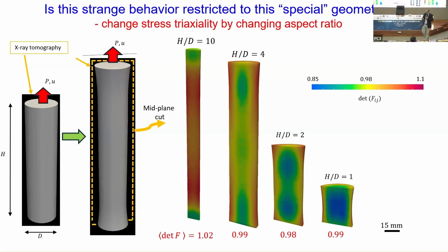And now what you can see is that this very long specimen was nearly incompressible in the middle. As you went shorter, you got more of this strange behavior. There's a little bit of green and a little bit of red. When you went shorter, now you're getting this blue and red, and then when you get even shorter, you get much more blue. So this problem seems to occur as you go shorter and shorter.